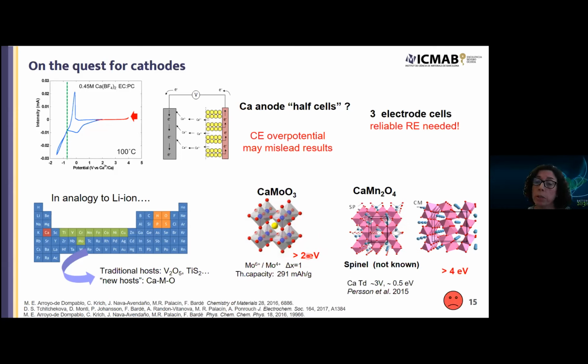We were also interested in CaMn2O4, and for this stoichiometry, there were calculations by the group of Kristin Persson in the US. She considered the spinel polymorph, which is not known because calcium is not that stable in tetrahedral position. But if it was possible to prepare this compound, apparently the migration barriers for calcium would be very low. So instead, we looked at the stable polymorph, which is the marokite one, which has these double rutile chains and these tunnels along the crystal structure, which looked very interesting.